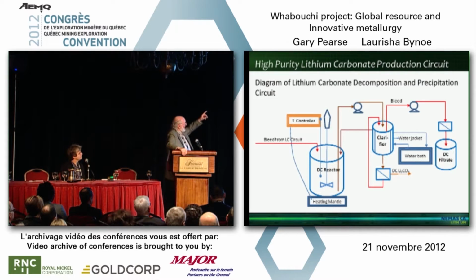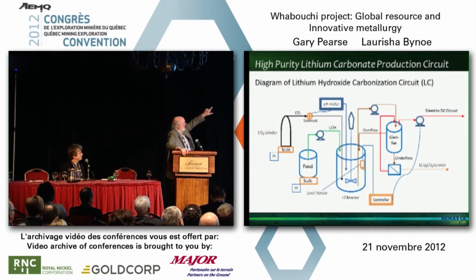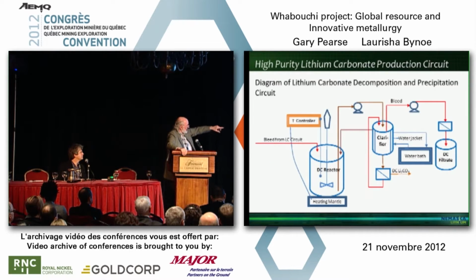one is you have the first one. I'm sorry, I should back up there. This is the lithium hydroxide carbonization circuit, and this in here is the main place where we make lithium carbonate from lithium hydroxide. So we're making two products here, the lithium carbonate and lithium hydroxide. And when you make this, you end up with a solution. You make a lithium carbonate precipitate plus a lithium bicarbonate solution that needs to be heated to drive off carbon dioxide, and then it will precipitate another final amount of lithium carbonate.